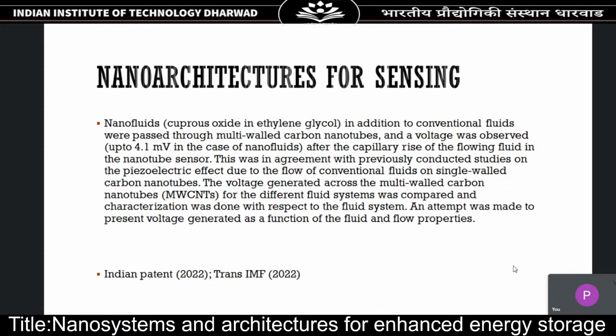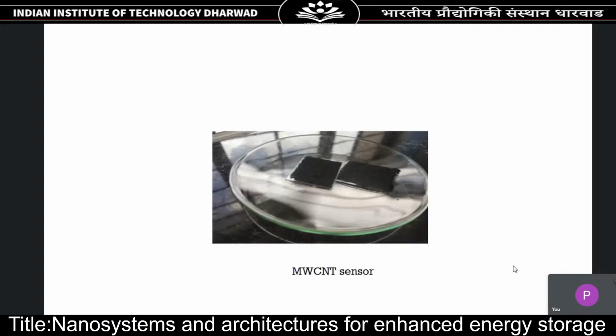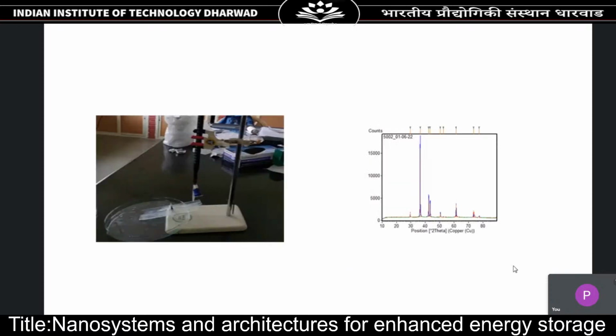And this was done for different nanofluid systems, and characterization was also done with respect to the fluid system. Recently we have published an Indian patent and also a paper in the Taylor and Francis journal Trans IMF. This is the MW-CNT sensor, which was used for the flow device. This is the setup of the device, and this is the XRD pattern of the copper oxide nanofluid nanoparticles.